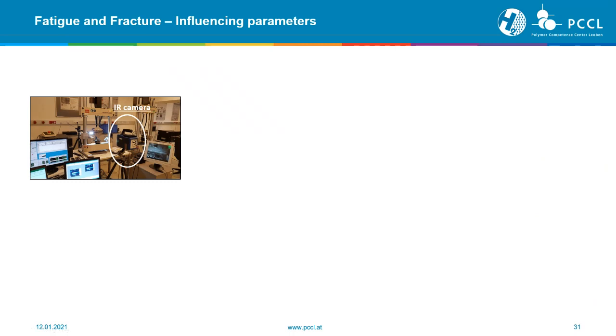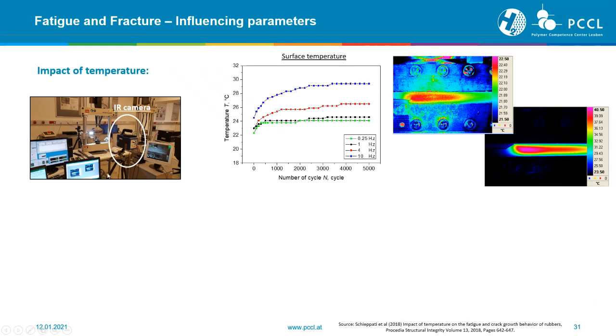Staying with the temperature, we also looked a little bit more into detail because when we talk about application time in terms of fatigue, in terms of hysteretic performance of the material, then temperature always plays an important role. And therefore, we've also applied an IR camera. What you can see here is the surface temperature as a function of the number of cycles for the different frequencies, as I showed you before: 0.25, 1, 4, and 10.